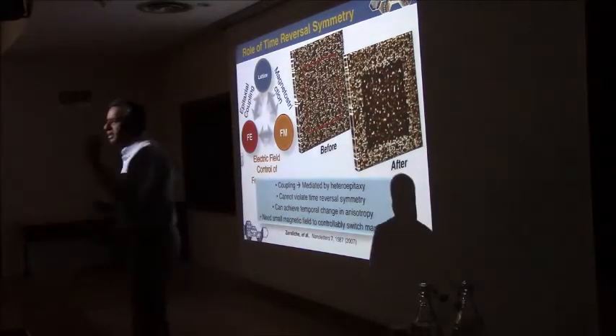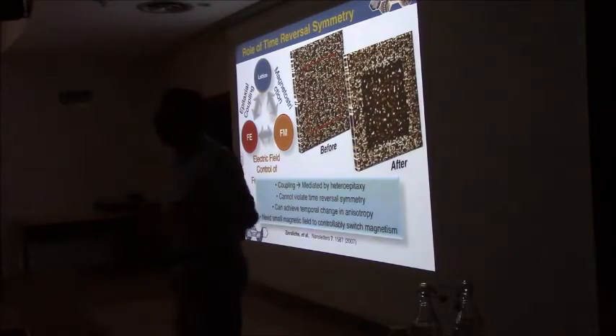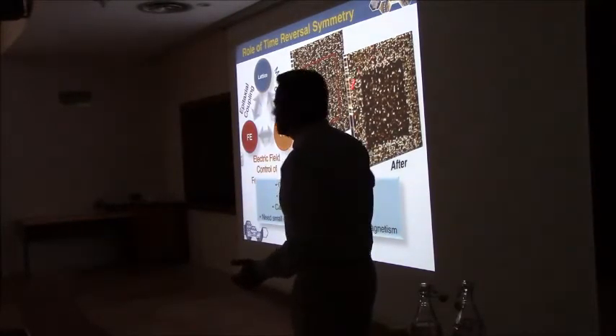At one point, it became very clear to us that this had to do with the fact that if you're switching magnetism, the direction of magnetism, you have to be able to break time symmetry. Otherwise, the data is not very clear. And therefore, when that dawned on us about 12 years ago, in the 2005, 2006 time frame, we said, oh, I just need to break time reversal symmetry. We applied a very small magnetic field, much smaller than the coercive field of the ferromagnet, typically 20, 30 oersteds of that sort. Immediately, we switched it completely. Okay. By applying a field in the opposite direction, I can completely suppress it too.